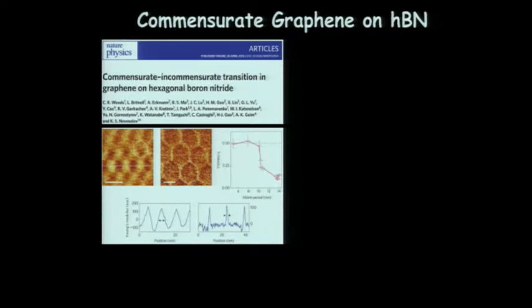And so there was this early report from the Manchester group here about the possibility of making the graphene be commensurate with the boron nitride. So the graphene lattice constant is 1.7% smaller than the boron nitride. And so their report here was that there was some transition at certain long wavelength Moiré patterns where they saw different things in their AFM, which they claimed then was a sign that the graphene and the boron nitride were becoming commensurate.